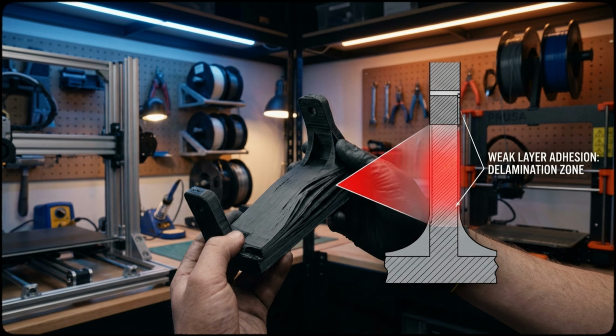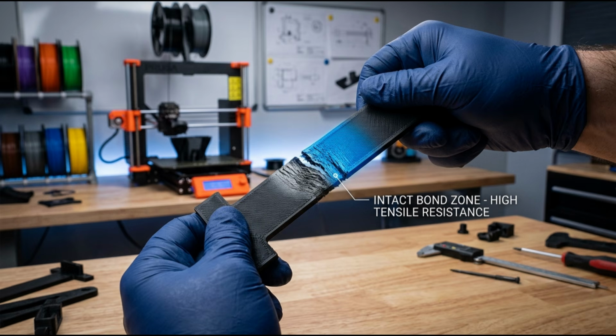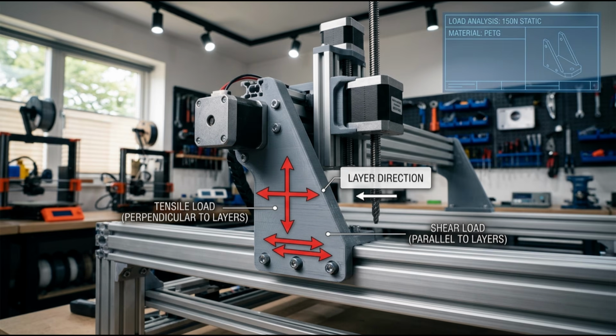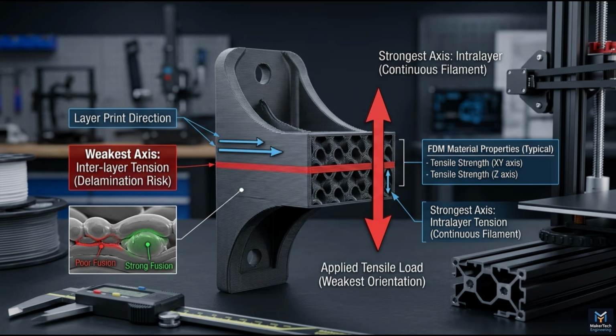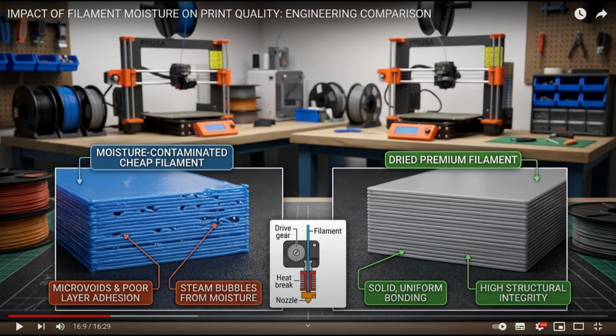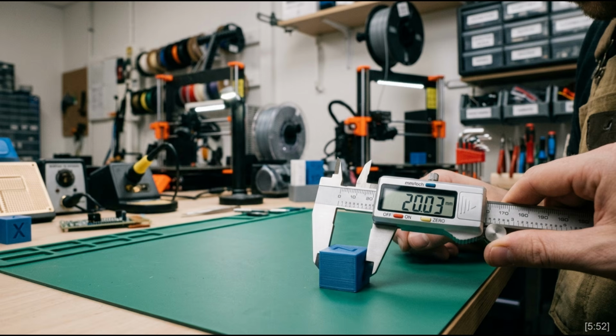On a poorly bonded print, the layers will delaminate with almost no effort. On a well-bonded print, you'll damage the material before the layers separate. This matters enormously for any print under mechanical load, especially parts loaded in tension perpendicular to the layer lines. That's the weakest direction in any FDM print, and cheap filament with moisture contamination can make it dramatically weaker.